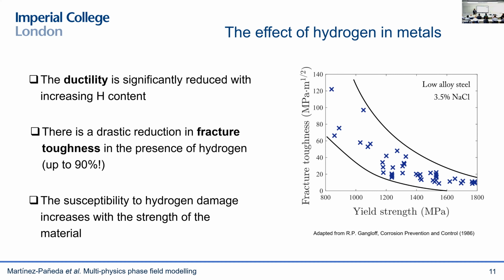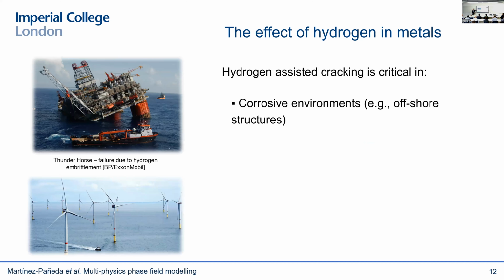And this is important for two reasons. One is that what this is telling us is that hydrogen has compromised decades of metallurgical research. So we have developed high performance materials, but we cannot use them. And the second thing is that we want to use high strength steels across many applications and sectors. And because they're more susceptible, this is triggering hydrogen assisted failures in otherwise very benign environments and in many applications where we never heard about this problem before. So traditionally, hydrogen was a problem related to aggressive environments, such as those relevant to offshore structures.